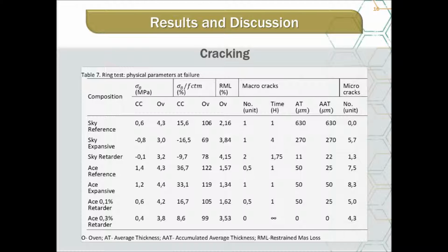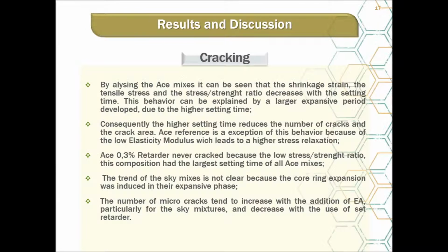ACE reference is an exception to this behavior because of the low elasticity modulus, which leads to higher stress relaxation. ACE 0.3% retarder never cracked because of the low stress/strength ratio. This composition had the largest setting time of all ACE mixes.